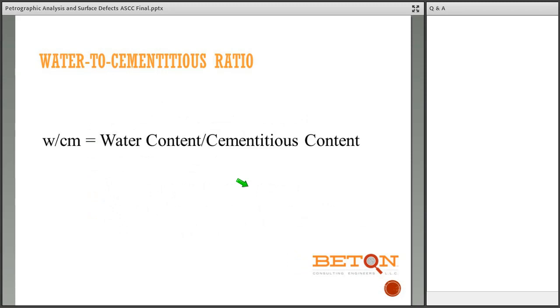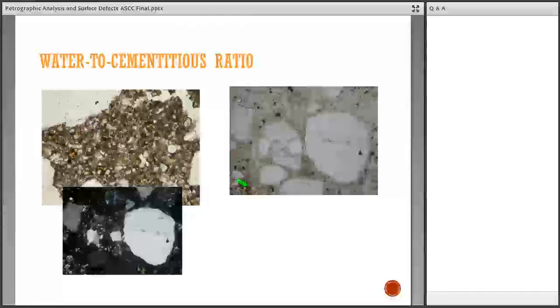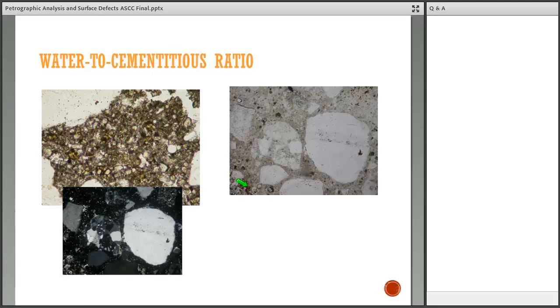Water to cement ratio, basically water content divided by the cementitious content. Basically, we'll make thin sections. We'll look at the amount of unhydrated Portland cement left in the paste. The one on the left has a lot of unhydrated Portland cement in it. You can see the unhydrated Portland cement clinker particles. There's quite a few. It's fairly thick with it. If you look at the one on the right, there's not as many. It looks more diluted and there's a lot of water. And then when you look at it in cross-polarized light, it's hard to tell here, but you've got a lot of larger calcium hydroxide or portlandite crystals.